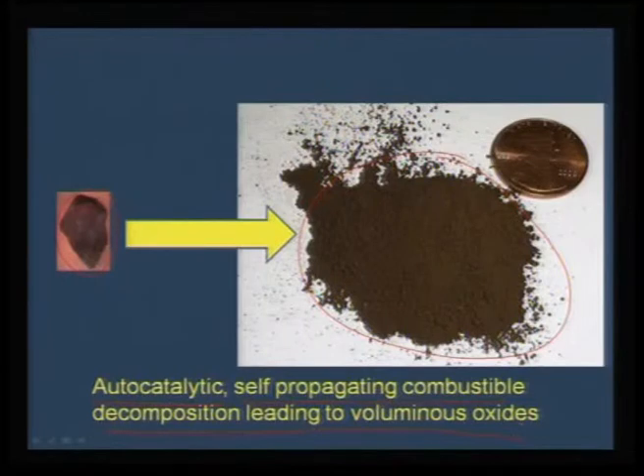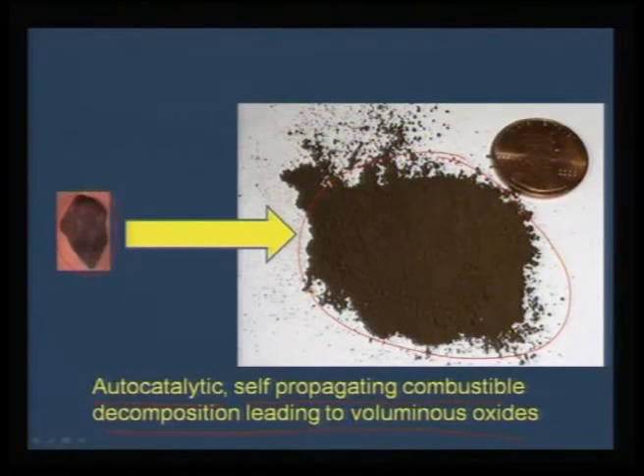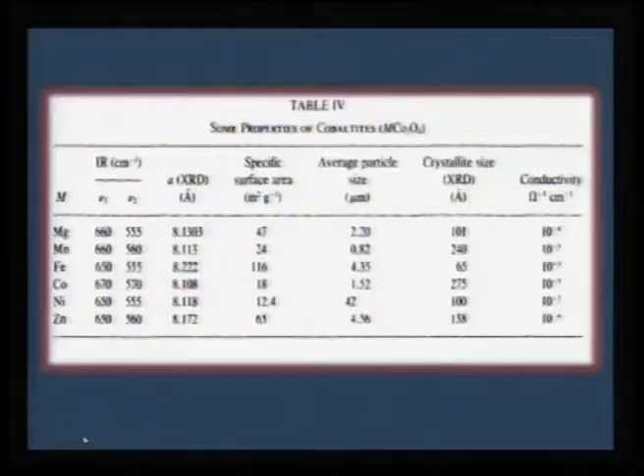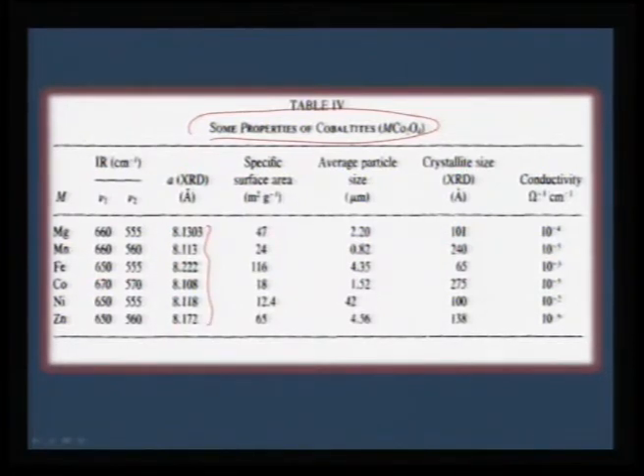But this may not be the true story when you look at simple precursors like nitrates, carbonates, sulfates or acetate precursors. They would not actually give you such a voluminous compound. When you talk about a voluminous compound, then you are talking about an increase in surface area. Therefore, it will be highly reactive and it can be used for many applications. These properties will be reflected in the oxide phase, and that is what we are seeing here in this table. Some properties of the cobaltites: the X-ray patterns all show that the cobaltites prepared with magnesium, manganese, iron, cobalt, nickel or zinc are all showing a cubic phase.